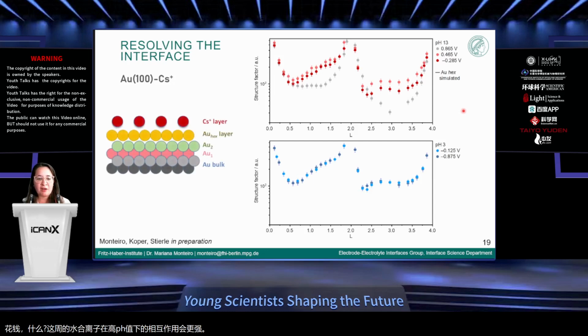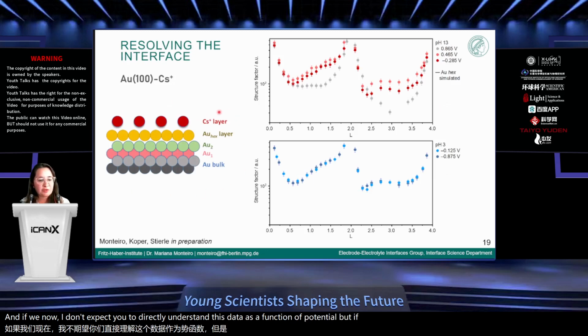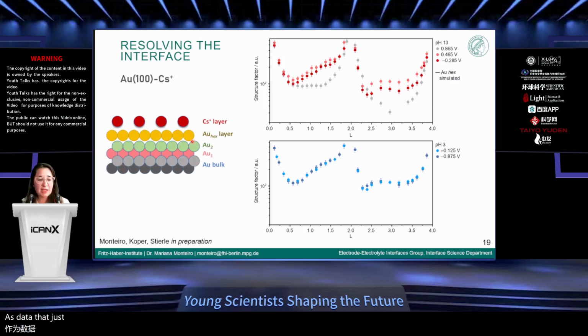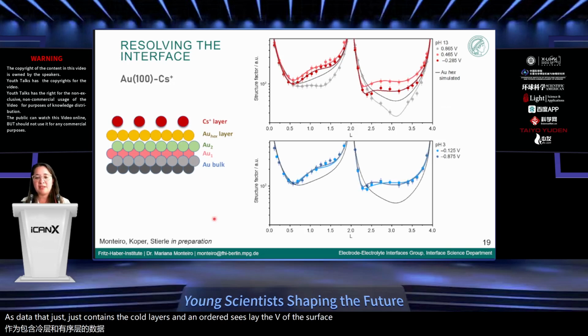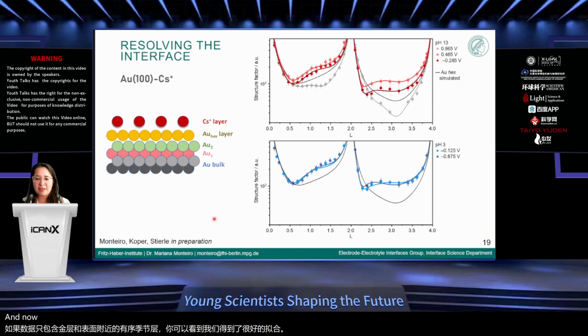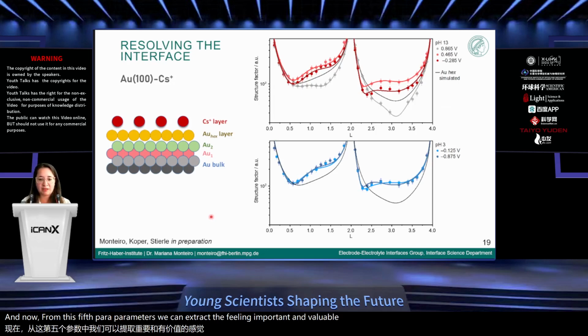And if we now, I don't expect you to directly understand this data as a function of potential, but if we now use a very simplistic model to try to fit this data that just contains the gold layers and an ordered cesium layer in the vicinity of the surface, you can see that we get very good fits for it. And now from these fit parameters, we can extract a few important and valuable quantities.